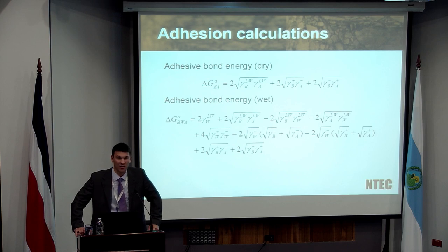Obviously, a higher debonding energy means that the material is going to be more susceptible to damage by moisture. And obviously, water, because of its nature, will always want to be more closely bonded with an aggregate than bitumen being bonded to that aggregate. So there's always that driving mechanism, but on its own, it doesn't tell you a lot.